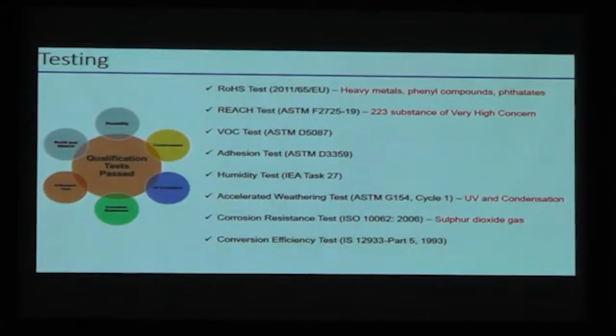So to utilize this coating for practical applications, the coating has to qualify various environmental tests, and in addition to that, it has to undergo the humidity test, condensation, corrosion resistance, all those tests. And all these tests were carried out under ASTM and International Energy Agency standards. We have tested these coatings at NABL accredited labs. They are third-party agencies, and they have evaluated and provided the certificate. The two major tests are the RoHS test and the REACH test. These two tests will give you the idea whether any hazardous chemicals are present in your coating or not.